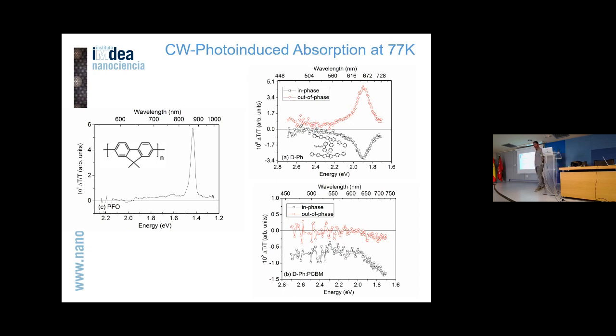So you are talking about the photostability. Yeah. So for many of them, for instance this one, it's a matter of minutes. If you are pumping in air, literally after 60 minutes that laser emission disappears. Minutes, it doesn't take long. So in order to avoid this problem, what people do is modification.